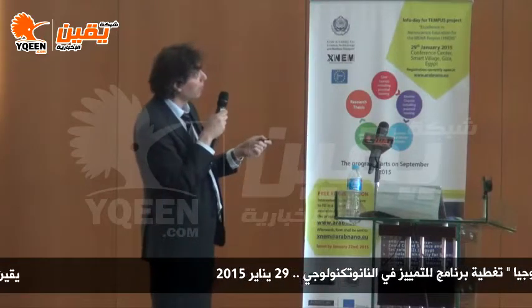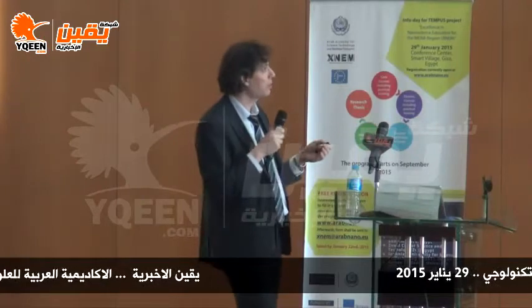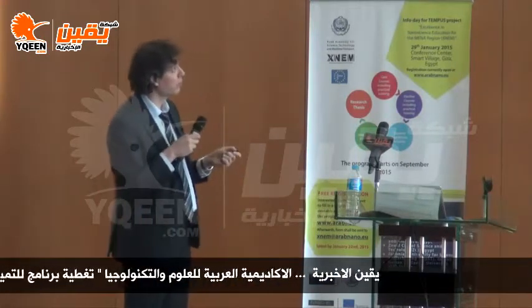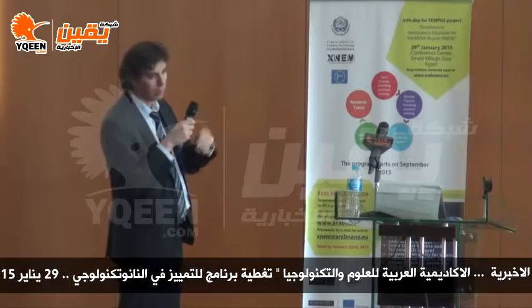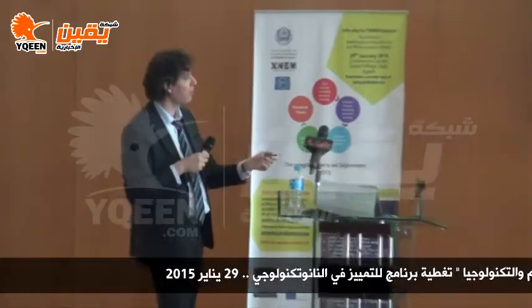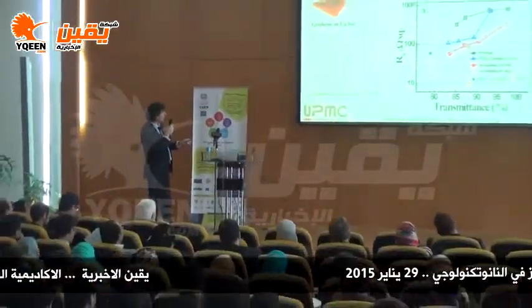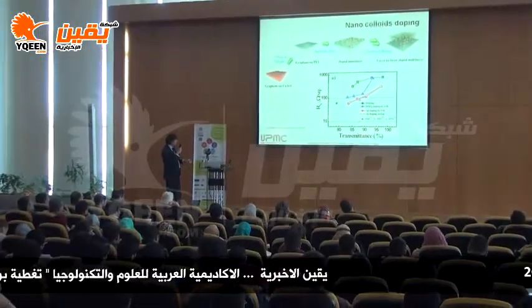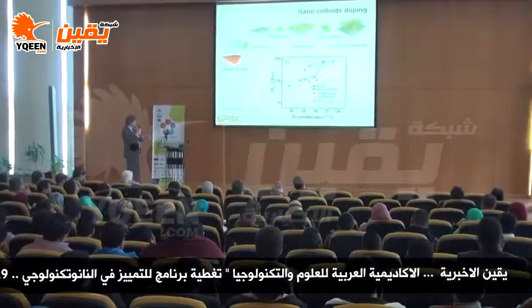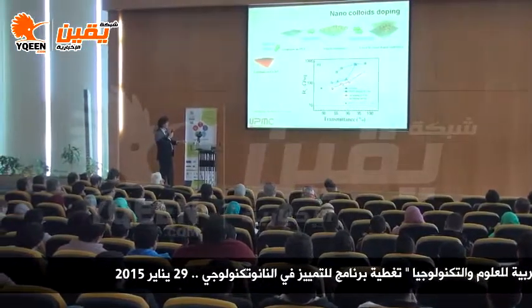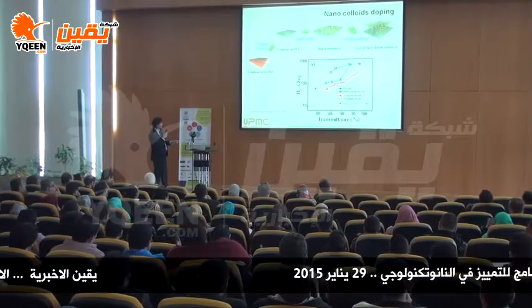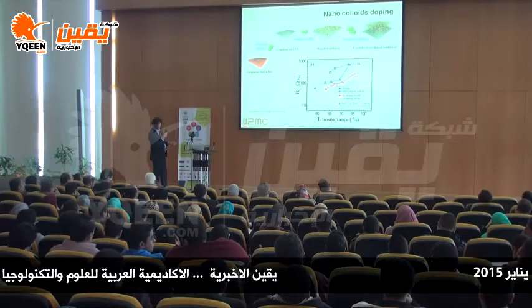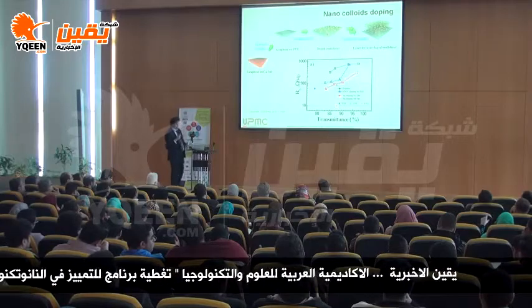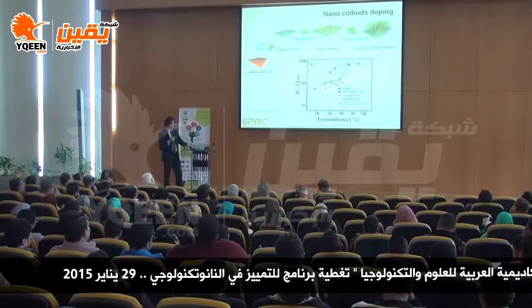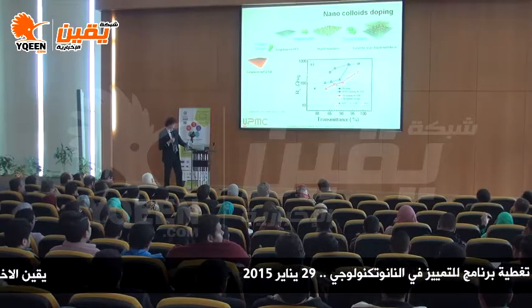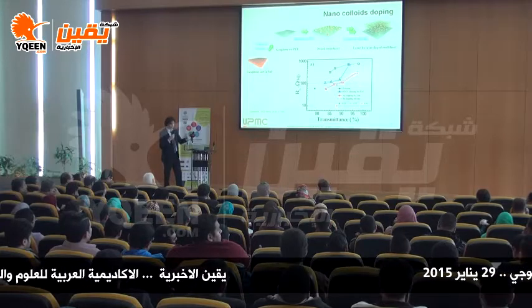This can be achieved by doping with nanocolloids, so particles that are 10 nanometers in diameter that we can drop cast onto the graphene. And we do that sequentially, like we sandwich those particles onto a few layers of graphene. Now, if we look here at the sheet resistance versus optical transmittance, we can see that with this process, we can be very competitive with ITO, here the blue star. So we have a few tens of ohms per square, and the transparency is still good. So there is room for optimizing. There is opportunity to replace ITO with graphene. Now the trouble is to get homogeneous graphene. That's another story, and that's very much dependent on the growth conditions.